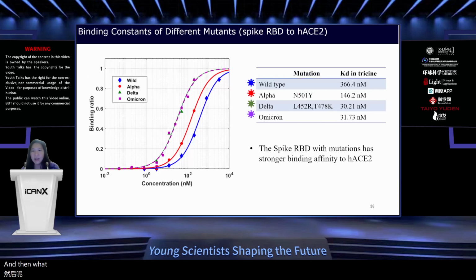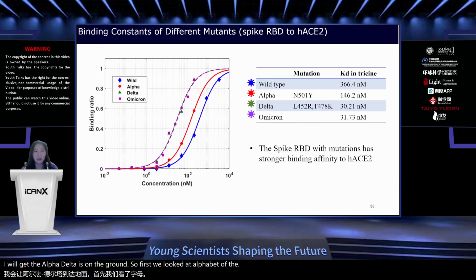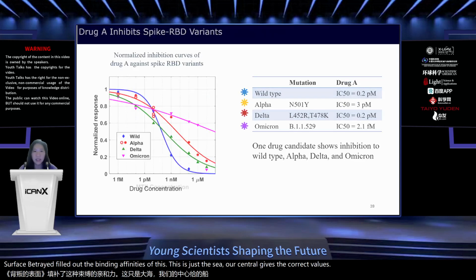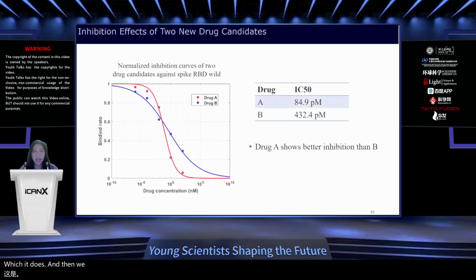And then what we did was we looked at different drugs that he found. We looked at the alpha, delta, and omicron. So first we looked at alpha, delta, and omicron binding to the surface. We pulled out the binding affinities of this. This is just to see if our sensor gives the correct values, which it does. And then we do this inhibition curve. So what we do is we mix in our drug with our SARS-CoV-2 receptor binding domain, and then we look at the different concentrations of the drug and see how much that inhibits the binding.